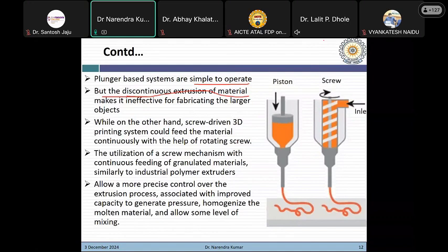So you can see we tried to make these kinds of components, and we were able to make them. Here we tried to make a chair, but unfortunately due to a power failure, this printing was stopped. But you can see the size and the curved surfaces. Even so, our setup was able to handle these kinds of surfaces and bigger sizes without any issues.